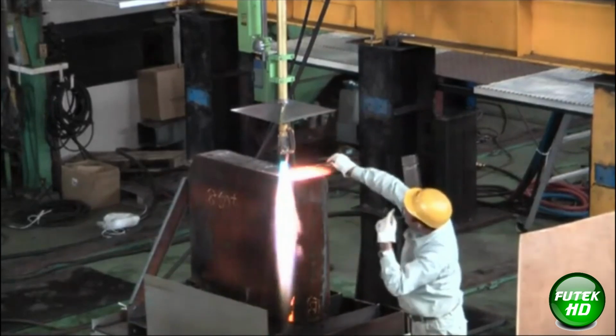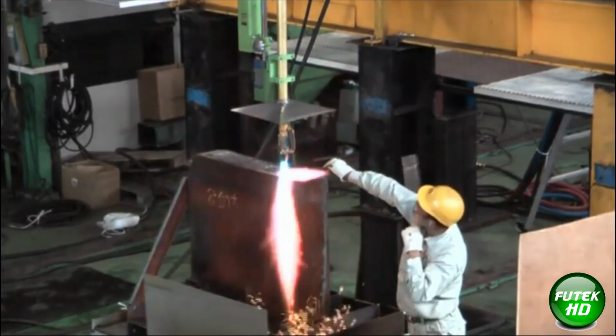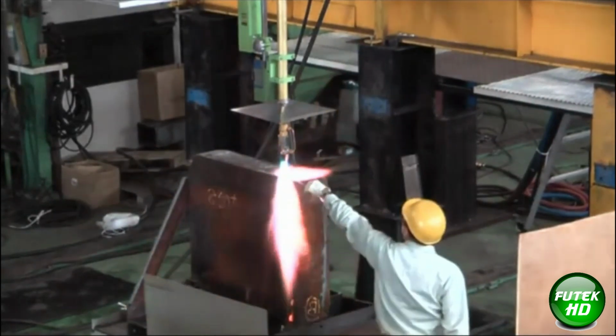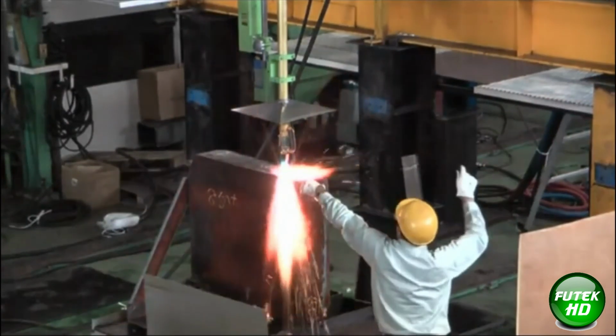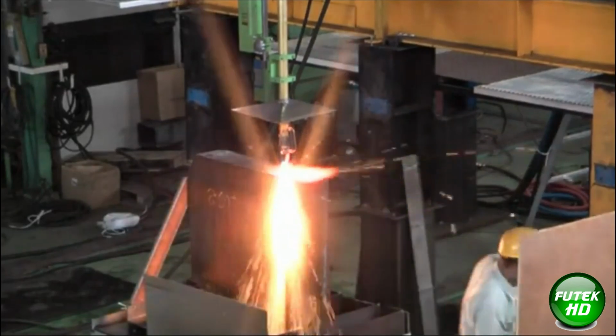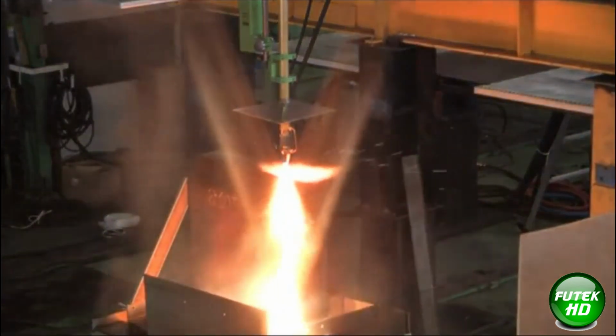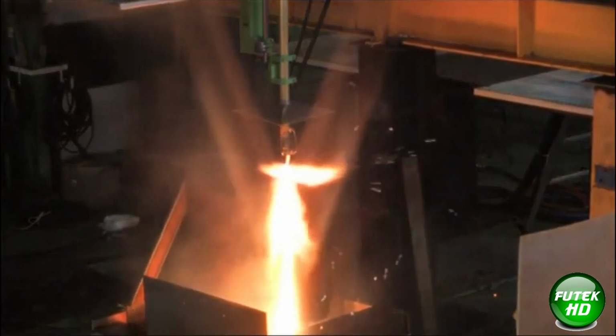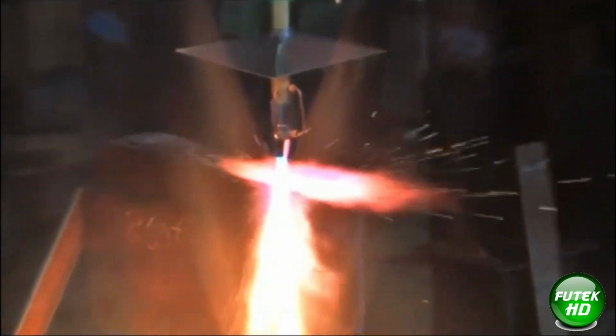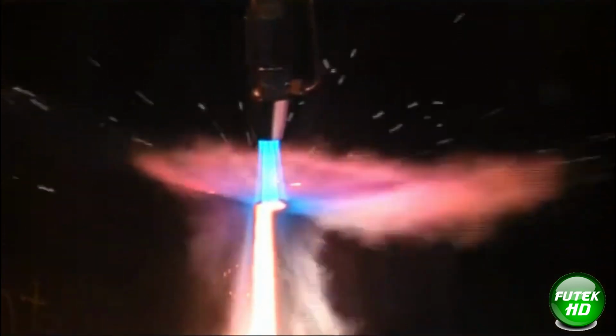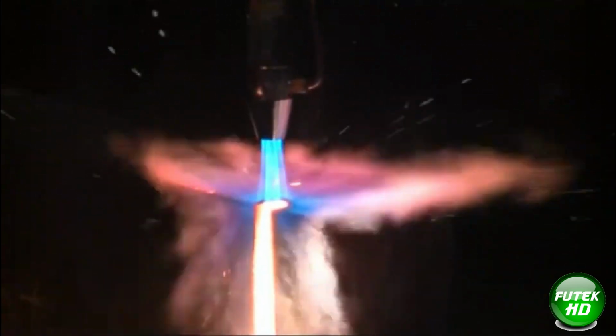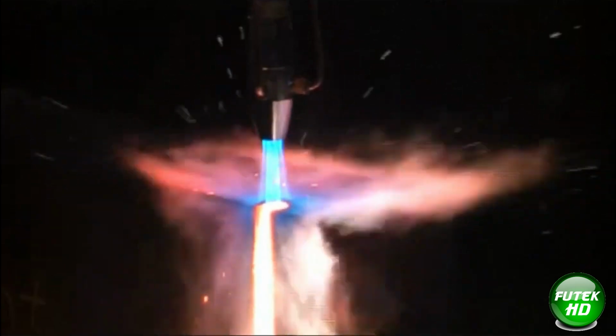Once the desired temperature is reached, a high-purity oxygen jet is directed onto the heated metal. This oxygen jet initiates an exothermic reaction with the iron in the steel, forming iron oxide, slag, while releasing additional heat, which sustains the cutting process. The oxygen stream also serves to blow away the molten slag, creating a clean cut. Cutting through 850 millimeters thick mild steel requires significant preparation and specialized equipment, including a high-capacity torch and a steady, controlled oxygen supply to maintain the cutting efficiency.